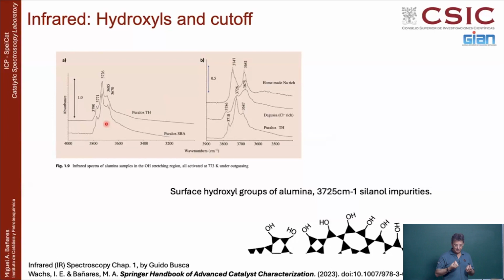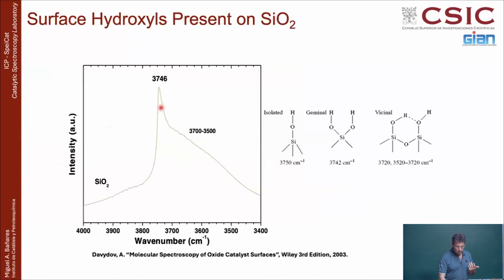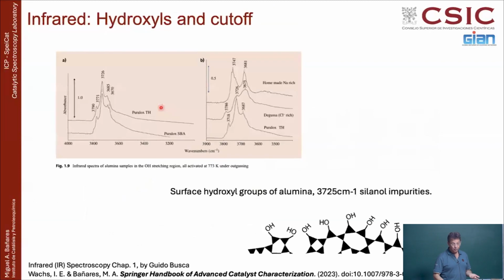Now that means that you have a hydroxyl here, and the other hydroxyl is in the other class. So there is no interaction between these hydroxyls. And then you get quite a sharp infrared vibration for these hydroxyls. In the case of alumina, zirconia, titania, many other oxides, you have a hydroxyl here, and another one here, and another one here, so there are interactions.